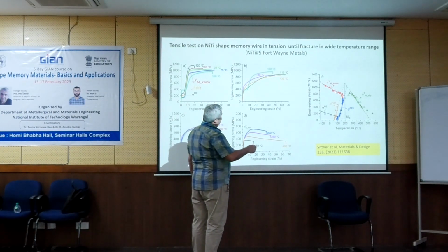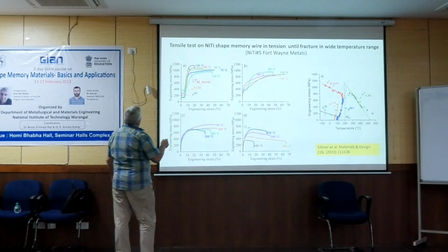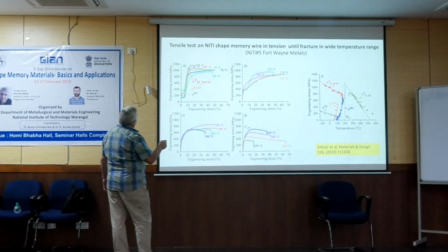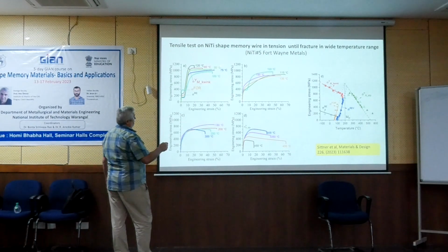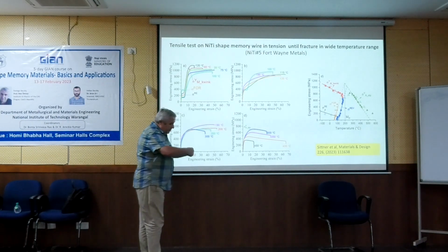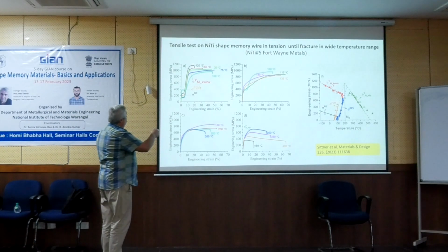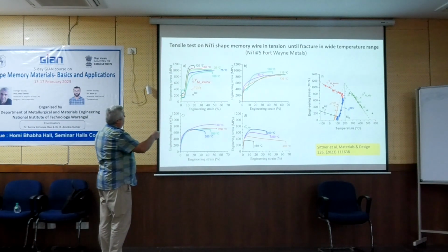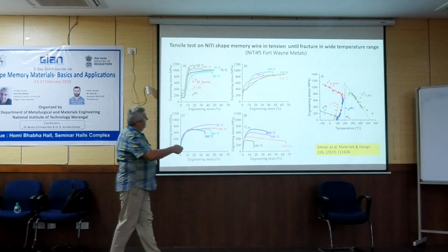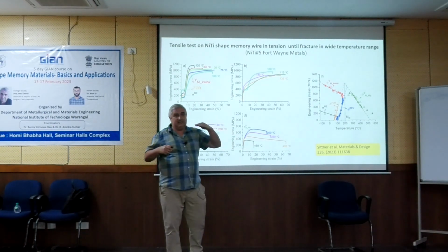Transferring this line here, when you are loading, the plastic deformation starts. This process which occurs during loading at constant temperature, like a plastic yield stress, proceeds here at constant stress. It can be initiated also by heating under constant stress.